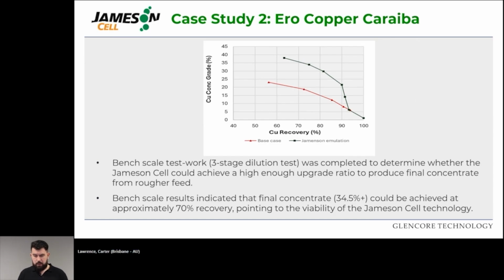So bench scale test work, our 3-stage dilution test, was completed to determine whether the Jameson cell could achieve a high enough upgrade ratio to produce final concentrate from rougher feed. The bench scale results were very positive and indicated that the final concentrate, which is a minimum of 34.5% copper, could be achieved at approximately 70% recovery, pointing to the viability of the Jameson cell in this debottlenecking project.